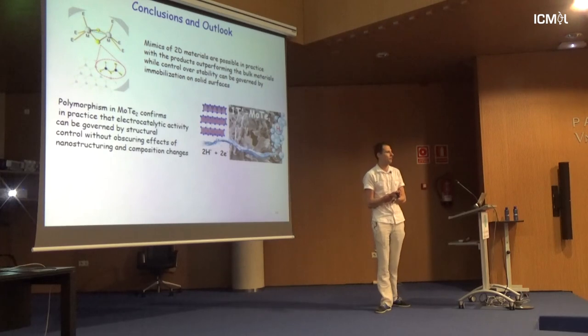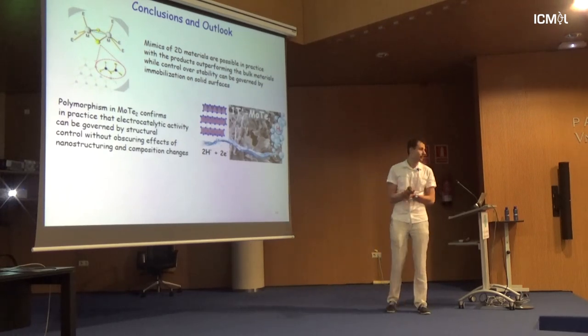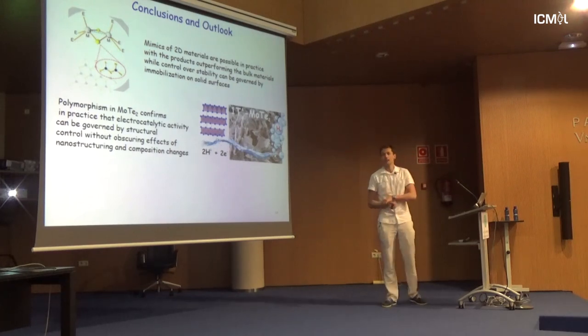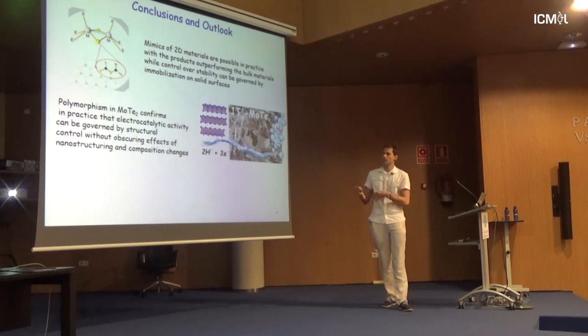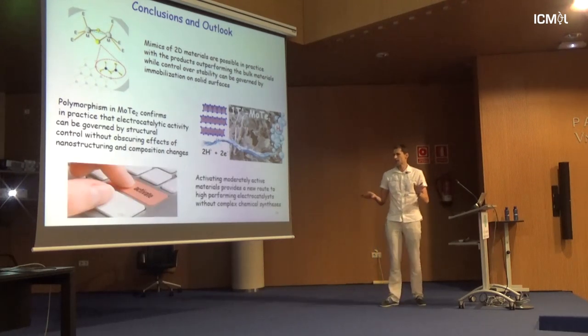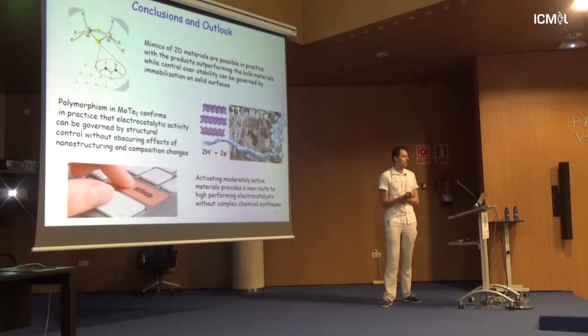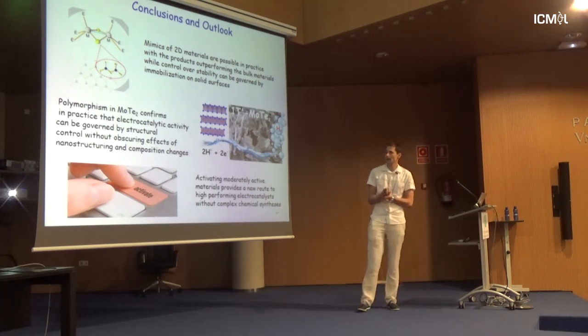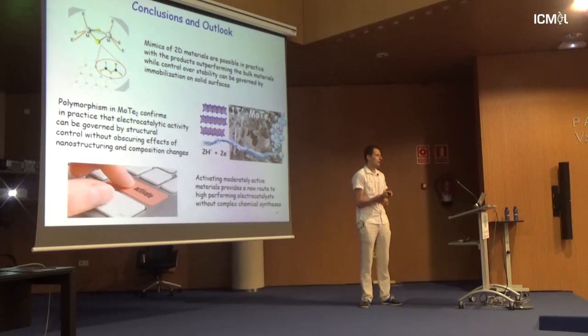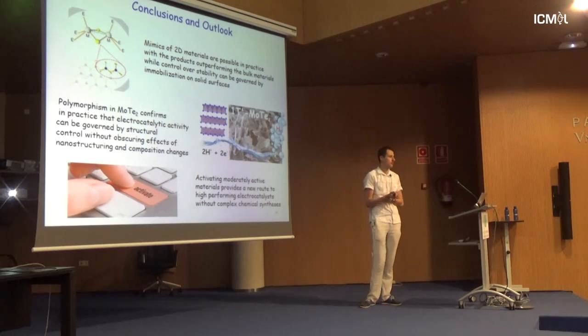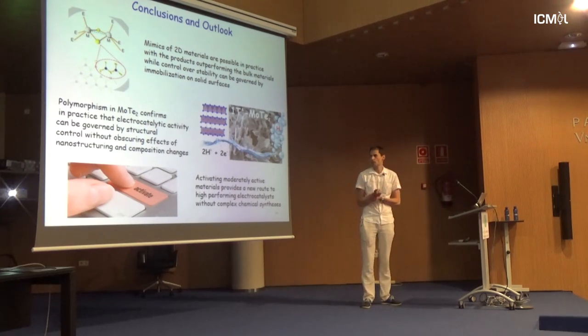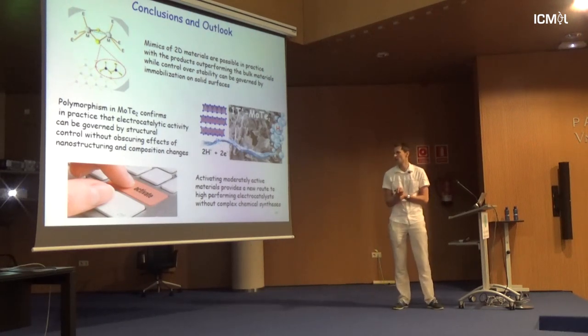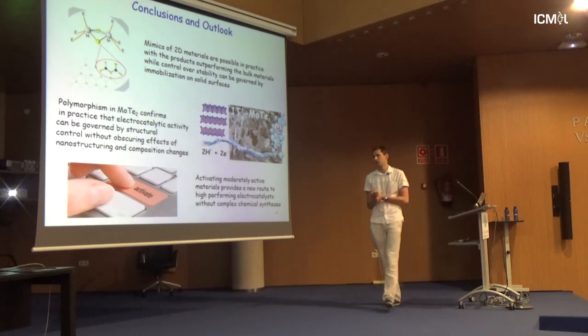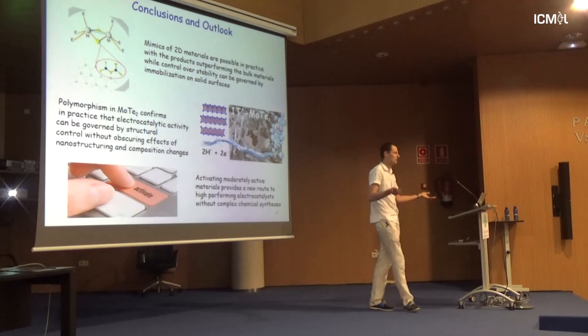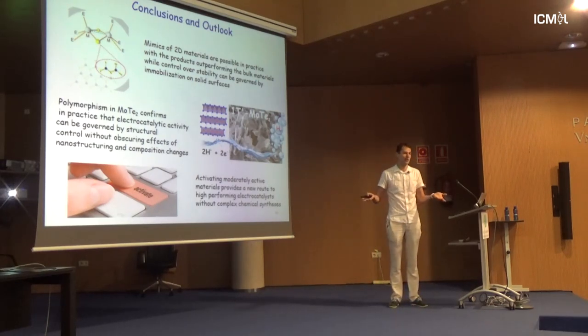There are plenty of polymorphic materials available in the literature, so this is something we are very keen to pursue, to see if the different polymorphs would behave differently. And a quite exciting direction that we are looking at very actively is the activation. We worked on different systems with limited success. Molybdenum telluride has the best performance. We found different systems which also show this, but not to this extent. So we still don't understand why it is happening. It's still puzzling, but this is how science works. If we knew the answers to everything, there would be nothing to do, and I would be working in batteries.